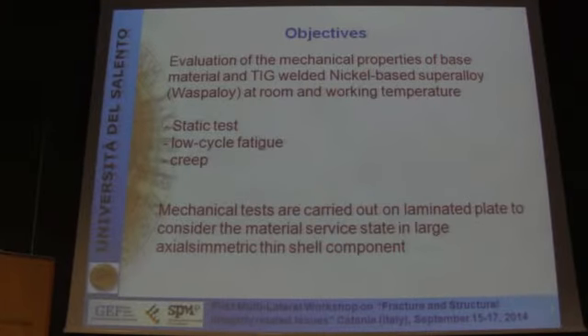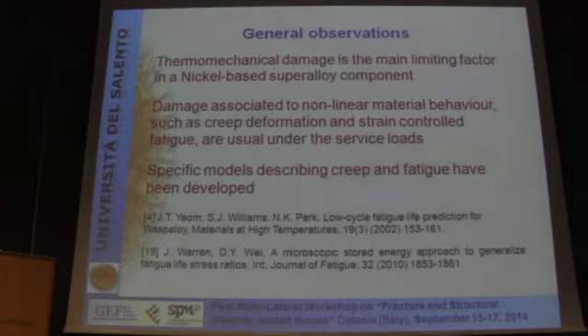To do the tests, we considered a laminate plate because this condition is more similar to that of a material used for high axial symmetrical thin shell components, like the casing of a turbo engine. Generally speaking, the thermomechanical damage is the most limiting factor of nickel-based superalloy components, and this damage is associated with the nonlinear behavior of the material under the usual service loads.